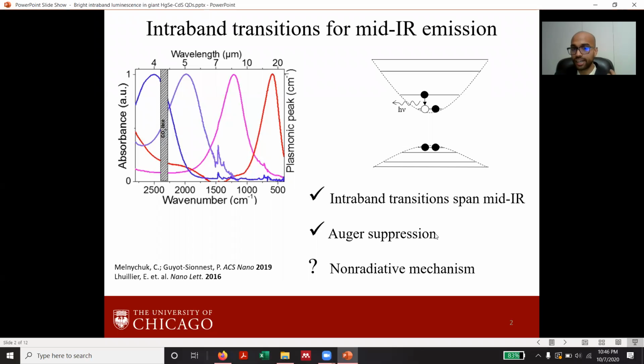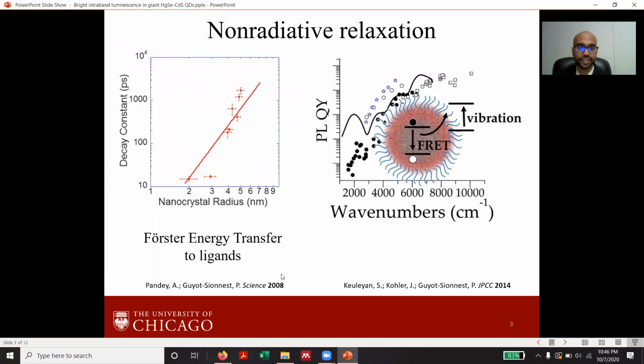Though a lot of studies have been done on intraband transitions in the mid-infrared over a decade, the mechanism of non-radiative relaxation is still not well understood. In 2008, Anshu Pandey and Philippe Guyot-Sionnest showed that the phonon bottleneck in the conduction band could be overcome by growing a giant shell on top of the core nanocrystals. They attributed the non-radiative decay as a faster energy transfer from the quantum dot exciton to vibrations on the surface. So we would expect a fourth power of the radius dependence of the lifetime with the size of the nanocrystal, which is what they observe experimentally.